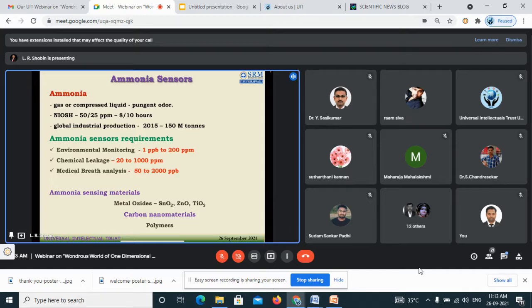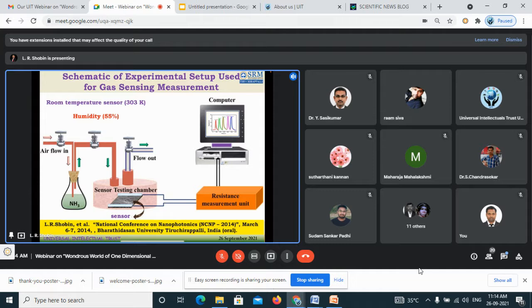Depending upon the level of the sensor, we can use it for different applications. Say for example, if it is a very good sensor with a parts per billion level of detection, you can go for environmental monitoring. If the sensor is able to sense more than 20 ppm, then you can go for chemical leakage detection in factories or somewhere. So far, metal oxides are used for the sensors. The carbon nanotubes are new for them. What I have used for this gas sensing setup is something like this.